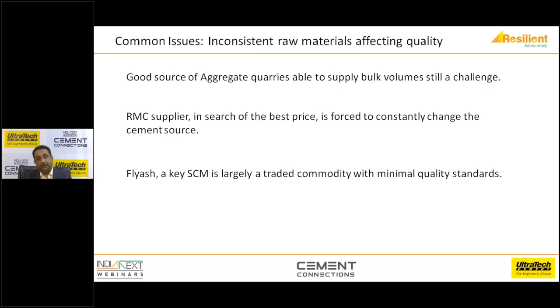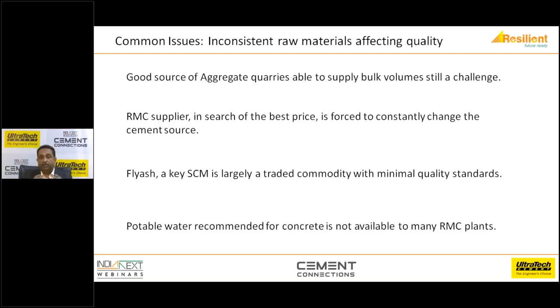While a lot of focus is on cement, aggregates, admixtures and fly ash, what people tend to overlook is the potable water quality. Potable water is recommended for making concrete, but the fact of the matter is most of the ready-mix concrete industry doesn't have access to industrial water supply or municipal water supply, and has to fall back on water suppliers or drilling their own borewell. The quality of the borewell water needs to be ascertained, because the chloride or sulfate limits could be beyond the permissible limits in some parts of the country at least. So this is an area where people need to focus.